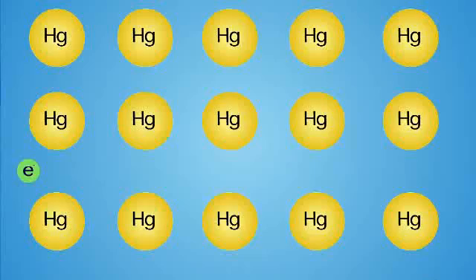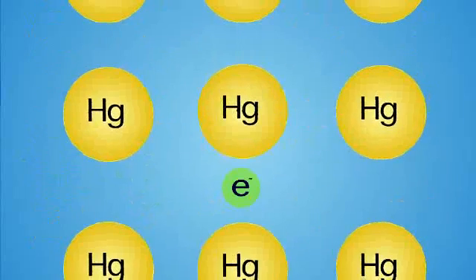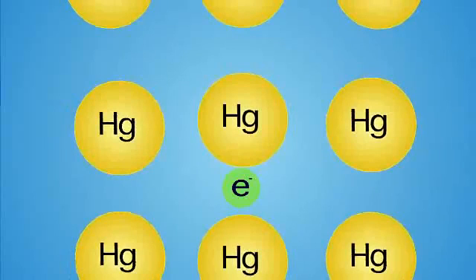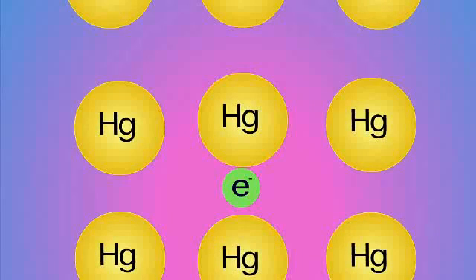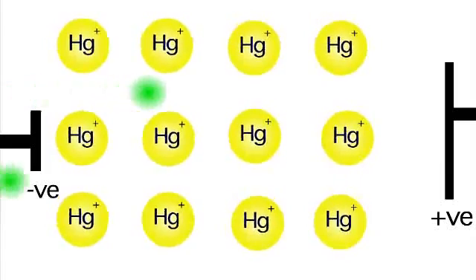Superconductivity can be explained in low temperature superconductors by BCS, or Bardeen-Cooper-Schrieffer, theory. It explains how Cooper pairs form and why they can travel through a metal with no resistance. To truly understand BCS theory you need to know some quantum mechanics, but you can roughly visualise it as follows. As an electron moves through the lattice, the positive ions are attracted towards it, distorting the lattice. This creates an area of temporary excess positive charge, which can briefly attract another electron towards the first. The lattice distortion allows the electrons to form a weak attraction. Once the Cooper pairs are formed, the lattice no longer has enough thermal energy to scatter the electrons in different directions. To scatter the electrons, which would result in resistance, the lattice would have to break the bond between the electrons in the Cooper pair. This is how the pair can carry the current through the metal with no resistance.